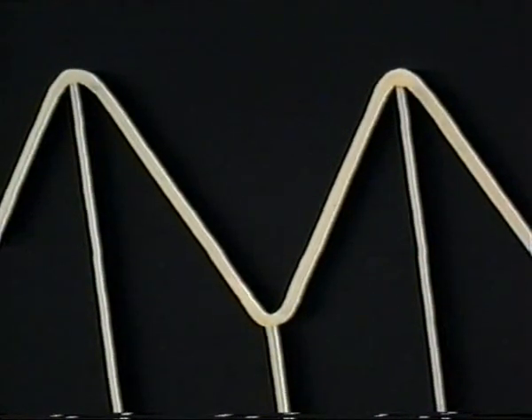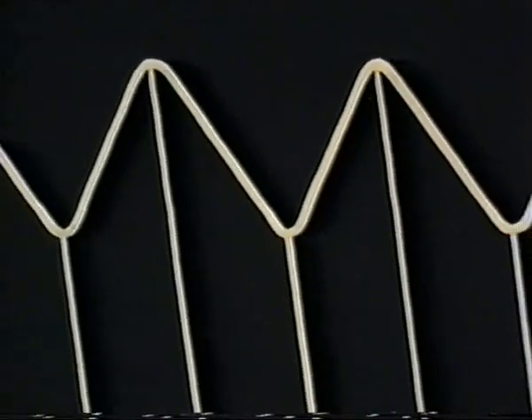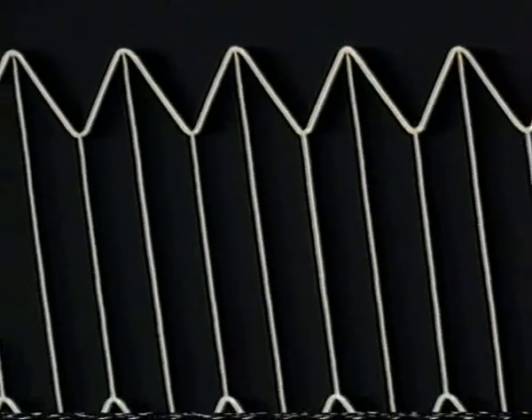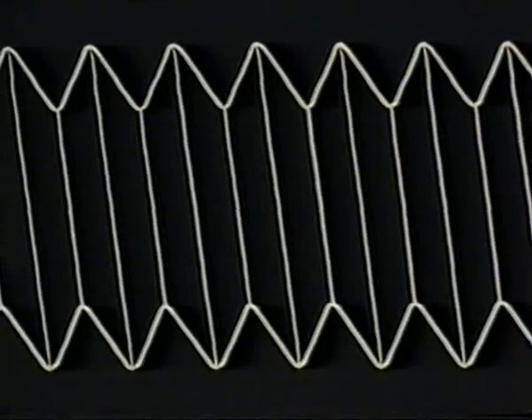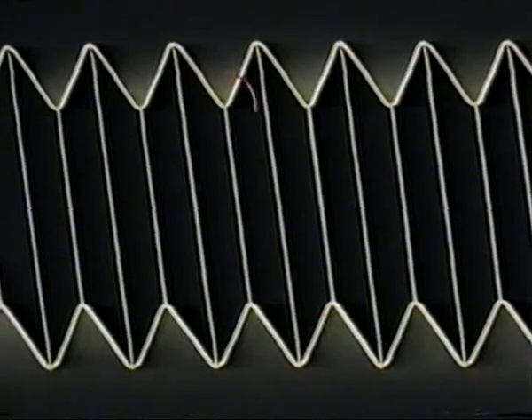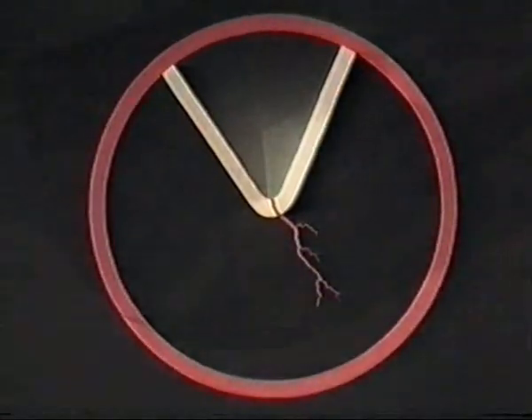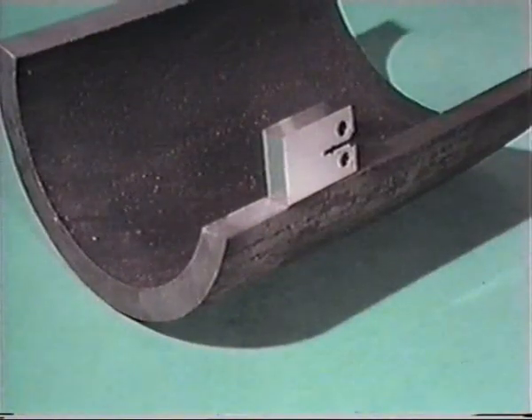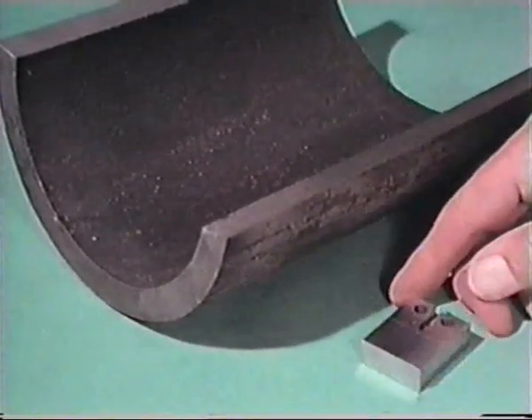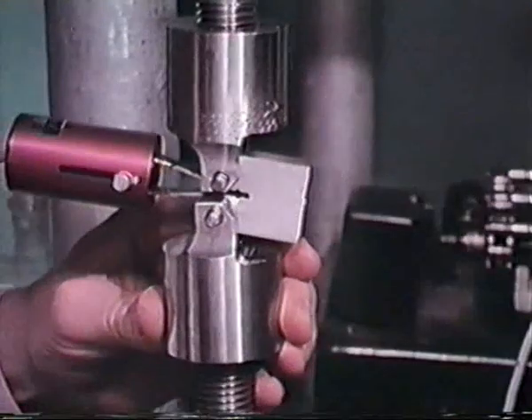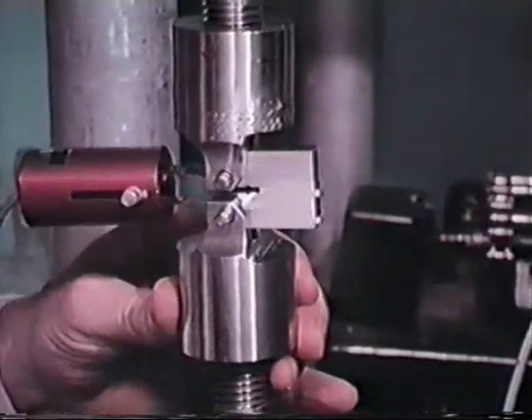Designers are familiar with the stress-raising property of notches, and where notches are unavoidable, as in a screw thread, appropriate allowance can be made in the strength of the material. But in a corrosive environment, at a stress at which it would normally be safe, a material can fail. This is stress corrosion cracking. For example, a section from a high-pressure pipe suspected of being liable to stress corrosion cracking was tested. A sharp notch was cut into it, and then a fine crack induced. The end of the crack is marked with a scored line. This crack acts as a severe stress raiser.